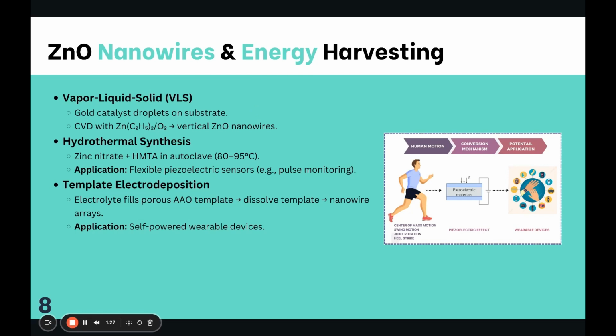At elevated temperatures, diethyl zinc decomposes and releases zinc vapor. Zinc and oxygen atoms dissolve into gold droplets, forming a liquid alloy. Upon reaching supersaturation, zinc oxide nanowires precipitate out and grow vertically from the substrate under the droplet.